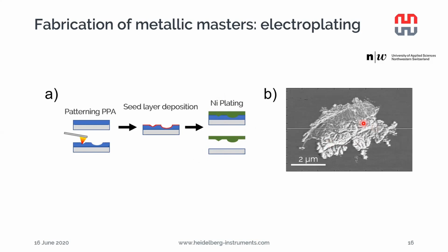Here's an example structure, the topographical map of Switzerland that was first written with NanoFrazor, and then nickel was electroplated on top, and we can see a very nice reproduction of the mountain tops and all the valleys of Switzerland in this.